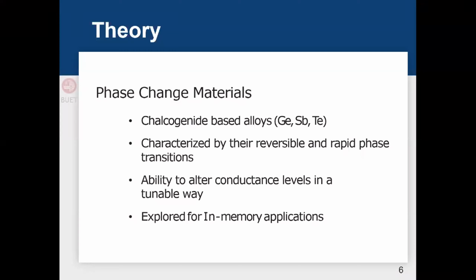So there is a large difference in the resistance across those states. Also, there are a lot of intermediate resistance states across these two. So there are not only two resistance states, there are multiple. They can be used actually for in-memory computation applications. In this work, we try to alter their temperature by applying different pulse techniques, different voltage pulses that will create Joule heating, and this will eventually switch their temperature to achieve different resistance states.